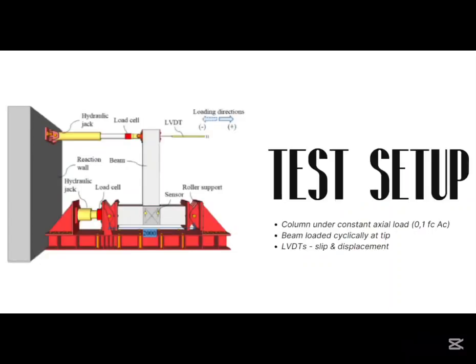Each specimen was rotated 90 degrees, so the beam was vertical. The column carried a constant axial load equal to 10% of its capacity. A hydraulic jack applied cyclic forces to the beam tip. Displacements and rebar slip were measured using LVDT sensors.